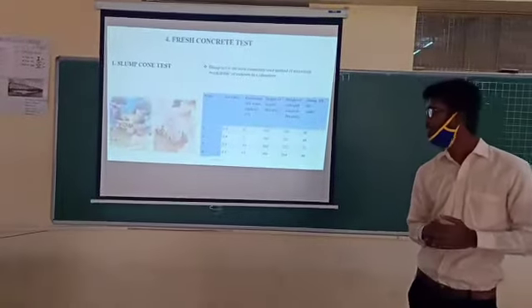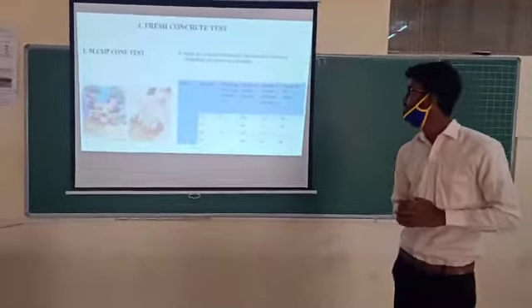We are conducting tests on fresh concrete. We got the results of the fresh concrete tests. Slump cone test: the slump cone is the most common method for finding out the workability of the concrete. These are the results we got for water cement ratio 0.4.